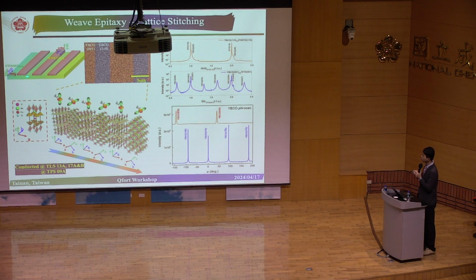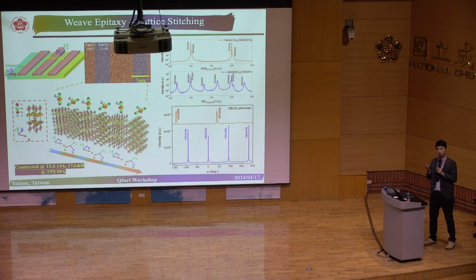What we essentially do is pick a substrate with 001 orientation, and on top of that, multiple stripes composed of 110 orientation. This is due to the growth nature. If you put the YBCO, which also has orthorhombic symmetry, on top of the rectangular pattern part, the C-axis will lie down in the plane. And if you grow the YBCO directly on top of the 001 orientation, you will find the C-axis along the out-of-plane direction. So this is the ultimate configuration. We can essentially control the C-axis, and then we can control the alignment of the dz squared orbital.